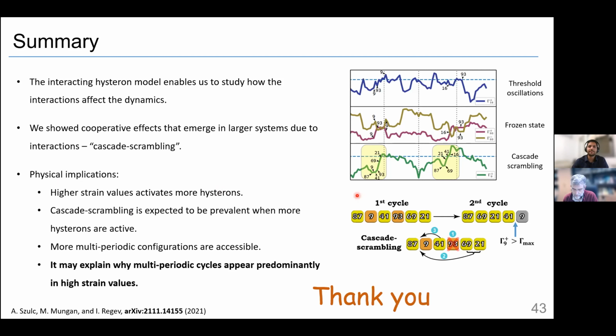In this model, we don't have a meaning to density because everything is random. So the proximity, or what you can expect for a dense system, is not here. So maybe you can relate it to hysterons that interact strongly, which by design is not the major part of hysterons. But we do see in particle simulations that we have regions of more dense soft spots, and we still have some in not so dense areas, and they are all interacting together. So I didn't mean spatially dense. I meant dense in strain.